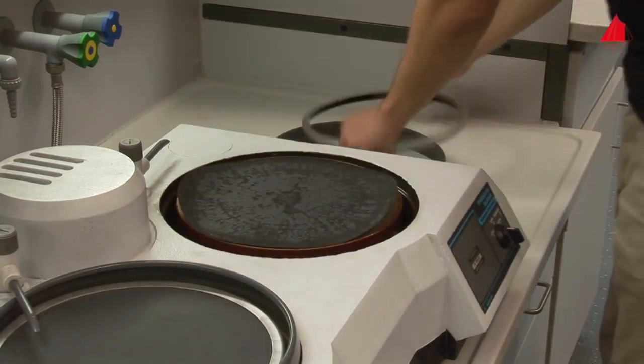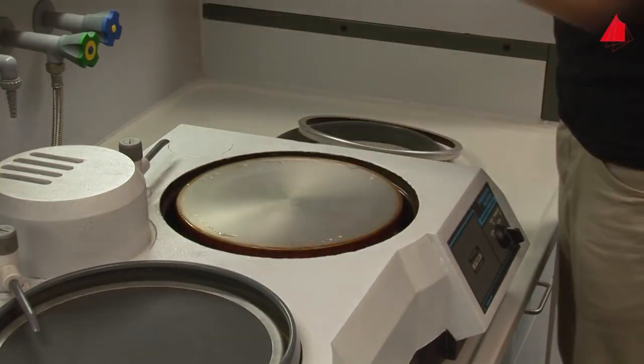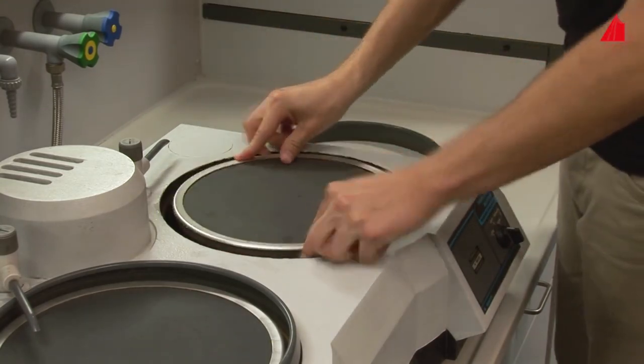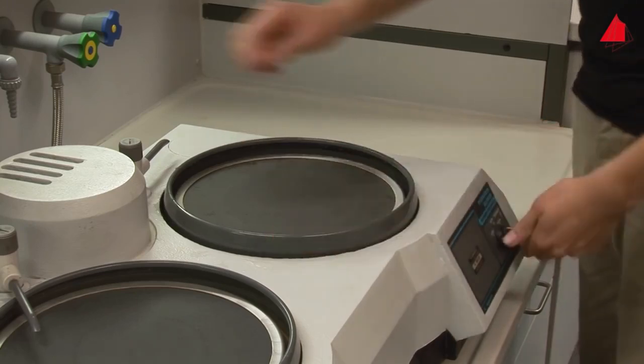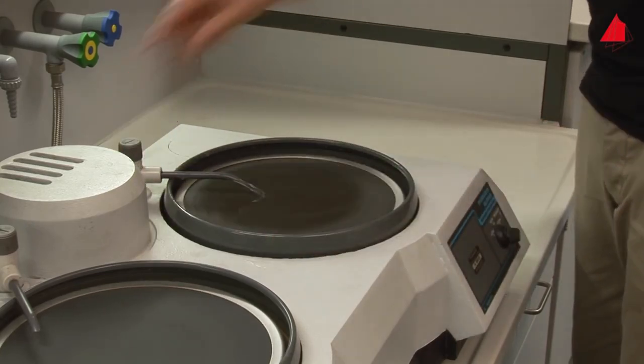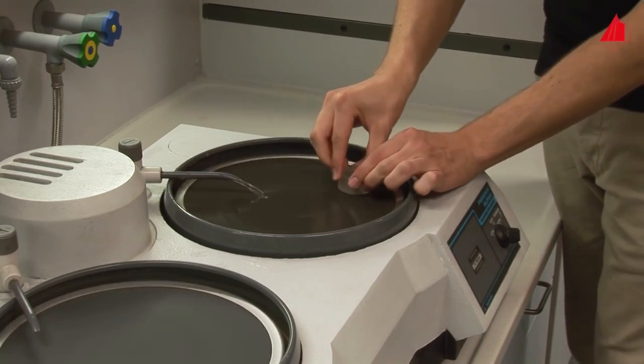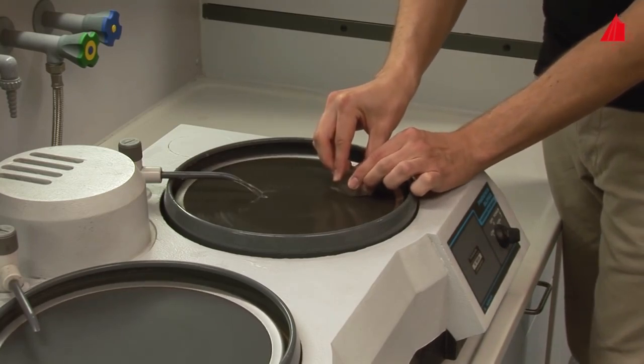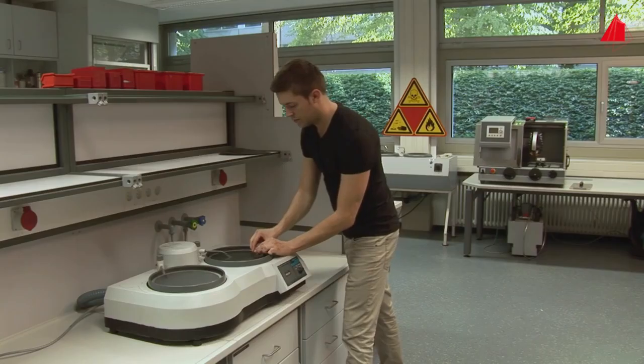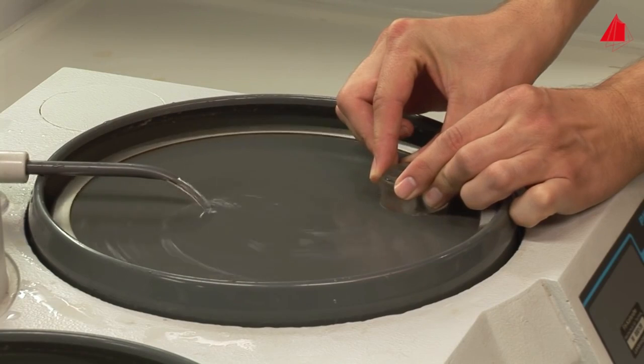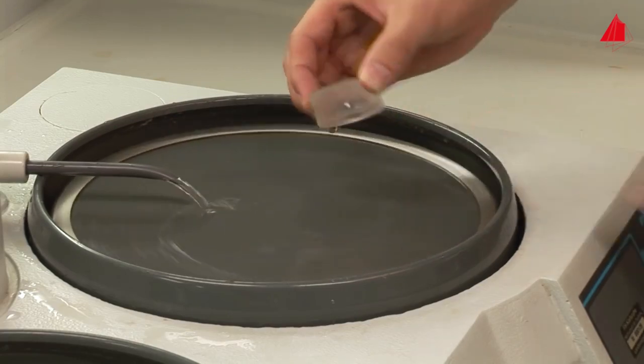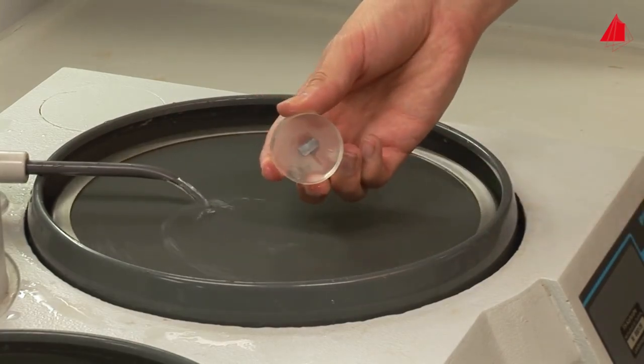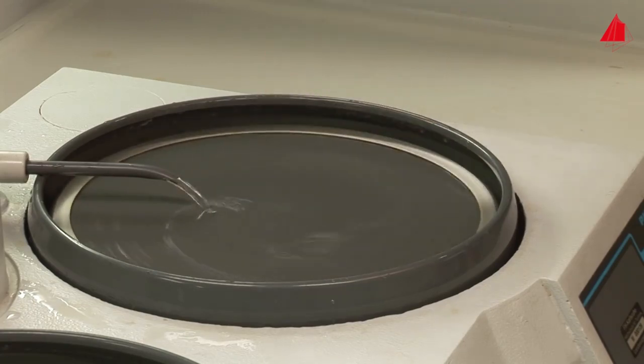He inserts a new 320 grit abrasive paper onto the disc. Rotating the specimen by 90 degrees leads to new grinding grooves perpendicular to the old ones. In this way, the material tester can easily check whether the old grinding grooves have been removed completely. It is important to use sufficient water flushing during grinding. This keeps the sample cool and prevents the abrasive paper from being loaded with material particles. Grinding continues with 600 grit and 1000 grit abrasive paper until an immaculate, finely ground specimen has been achieved. The specimen is now ready for polishing.